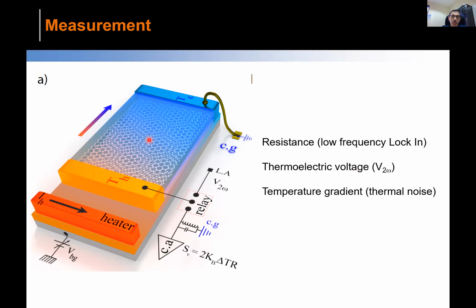So this is your twisted bilayer graphene. As I was telling, it is connected by these two contacts, and this heater creates a temperature gradient. There are two important things you have to measure, as I was telling you. What is this voltage difference? That is a very well-known technique, which you can do by the so-called 2-omega technique, which is standard. But the main difficulty is to measure this temperature difference.